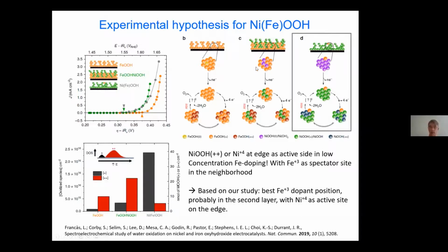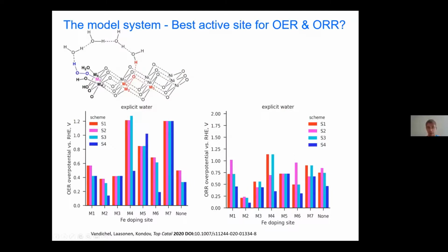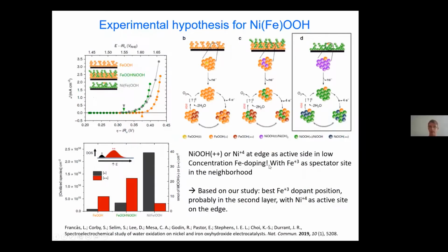By the way, this is just some extra information. If we would work with a higher iron concentration than we have here in C, then we would actually have iron 4+ and nickel 3+. So that surprisingly changes the whole story. But in our system, we found that the best iron doping site was M2 here, that's in the second layer, that gave the lowest overpotential, both for the OER as for the ORR process. So that seems to correspond quite well with the active nickel 4+ that we have, and so that seems to confirm this experimental study.